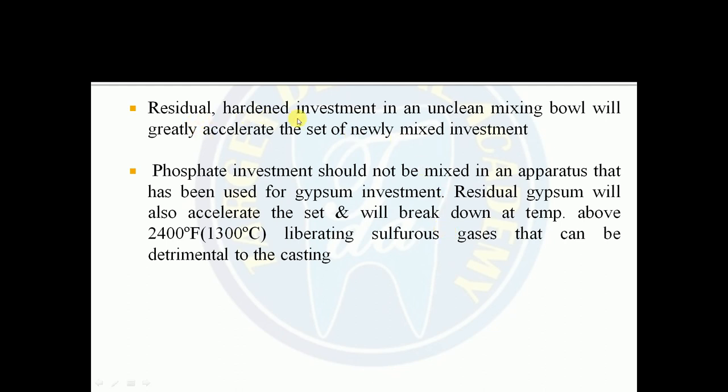Residual hardened investment in an unclean mixing bowl will greatly accelerate the set of the newly mixed investment. The phosphate investment should not be mixed in an apparatus that has been used for gypsum investment. You have to keep this in mind, that your apparatus should be clean. Residual gypsum will also accelerate the set and will break down at temperatures above 2400 degrees Fahrenheit, liberating sulfurous gases that can be detrimental to the casting. So make sure that your apparatus is clean.